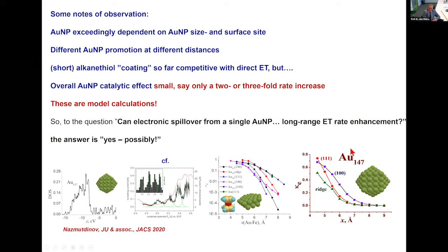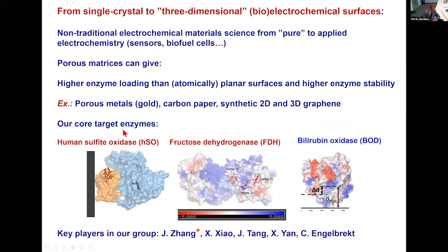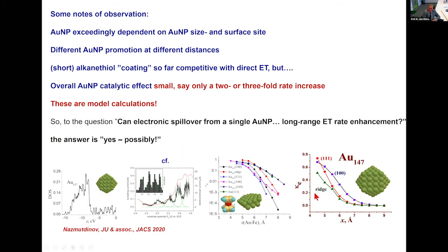And it turns out if we take the most realistic gold nanoparticles of the ones we could calculate, we couldn't calculate anything bigger than 147, then the planar gold actually outwins most of the particles, except the gold 100 particle. There you can see there is actually a catalytic effect, if you can call it that. It is not a factor of orders of magnitude. It's a factor of 2 or 3, which is, however, quite rewarding.